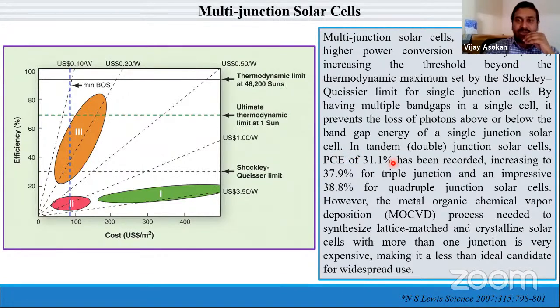So in a tandem, that's a double junction solar cell, the recorded efficiency was 31.1%, which increased up to 37.9% for a triple junction and up to 38.8% for quadruple junction solar cells. However, the metal organic chemical vapor deposition process needed to synthesize lattice matched, crystalline solar cells with more than one junction is very expensive, because when we are making different materials with different lattice parameters, there may be a lattice mismatch from one material deposition to the next. So it again causes energy losses, including defects and interface issues. So again, the efficiency can be reduced even with multi-junction solar cells.